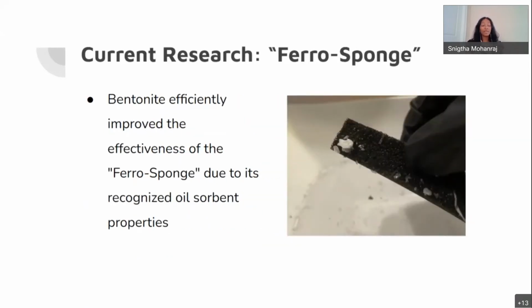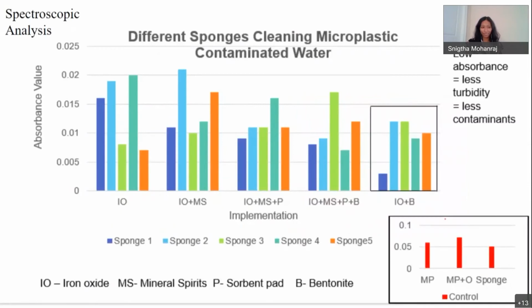But as expected, bentonite was able to efficiently improve the effectiveness of the ferrosponge the most, since it has recognized oil sorbent properties. And this is demonstrated in the picture to the right, where it was able to successfully remove microplastics and oil in contaminated water.